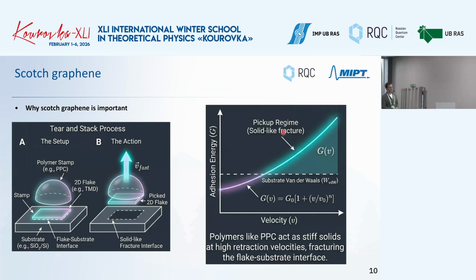So, the dependence of the adhesion energy on the velocity. It turns out that there is some specific value, and it also depends on the speed at which you remove it. Depending on how fast you do it, you can either tear the 2D material off the substrate, or it will still be there. So you must play with these parameters, like the speed of detaching, and then you can obtain your material on the stamp. And then you will ask me, why do it?